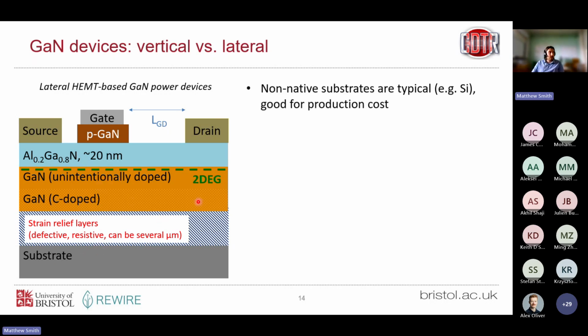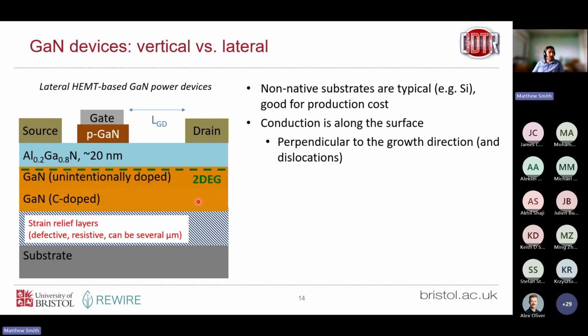So that's non-native substrates. Typically silicon is used for power devices, which is great for production costs because silicon is very cheap. Conduction is along the surface in these lateral devices, and that's perpendicular to the dislocations. When we grow this gallium nitride layer on non-native substrates, we get dislocations in our structure, which are extended defects in the crystal, essentially misalignment of atoms, and they point vertically towards the surface. They go from the substrate towards the surface, but our channel is perpendicular. Our conduction of this 2-DEG is perpendicular to those dislocations.